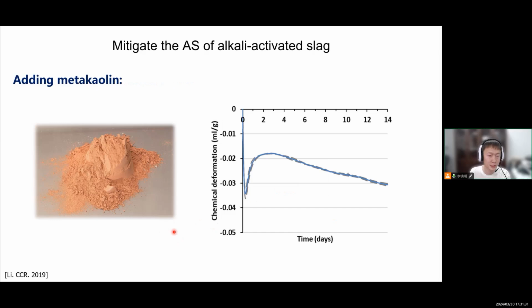And then another way to mitigate the shrinkage is by adding metakaolin. So my initial idea is, alkali-activated metakaolin can show chemical expansion, and alkali-activated slag can show large shrinkage, and AAMK can release water, expel water, and AAS needs water. Then maybe the water can compensate each other, can internally cure each other. That is my initial idea, but then this idea failed, because from the chemical point of view, when you mix metakaolin together with slag, they will not be two separate systems anymore. They are actually a blended, mixed system, and the reaction products will not be N-A-S-H gel here and C-A-S-H gel there, and then they internally cure each other, but actually they become a blended gel, and it will not have two separate systems anymore. But the result is not bad.